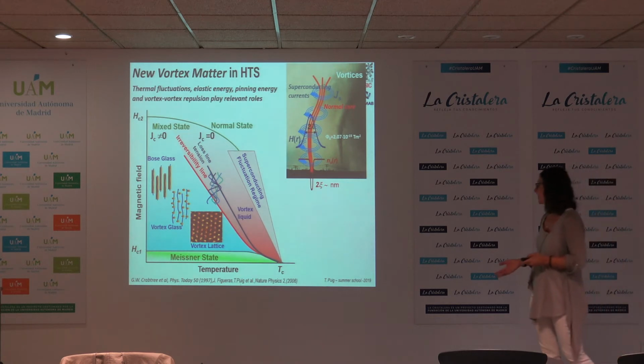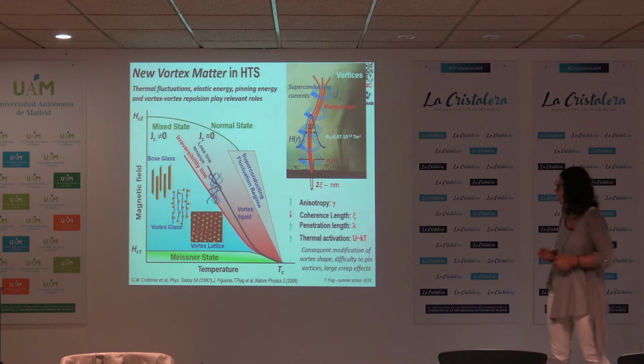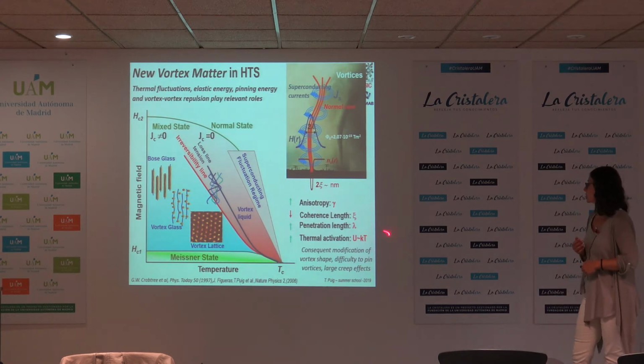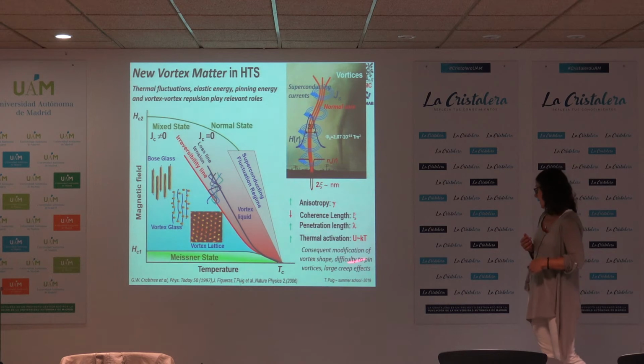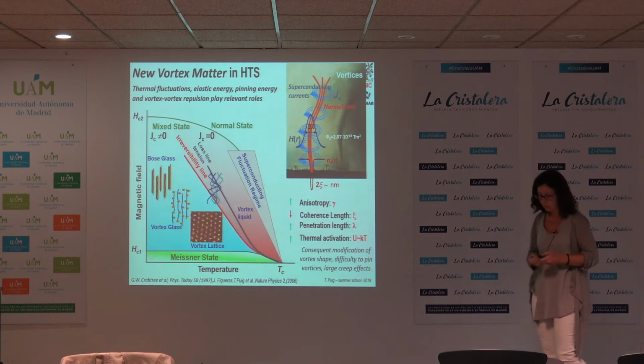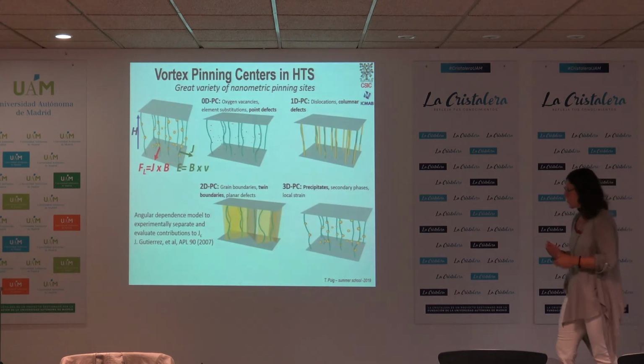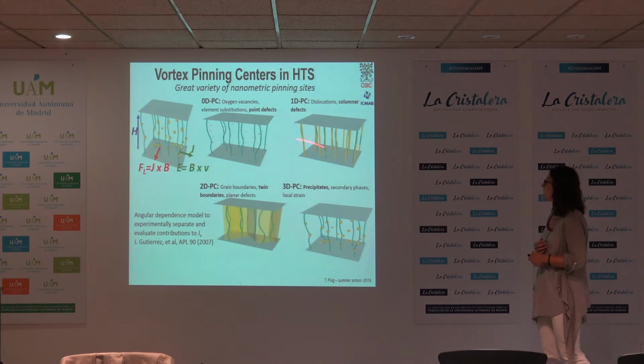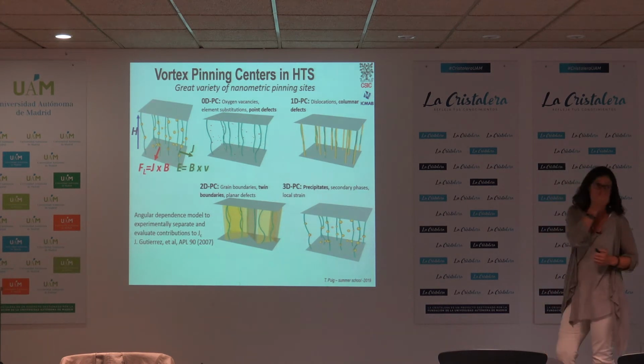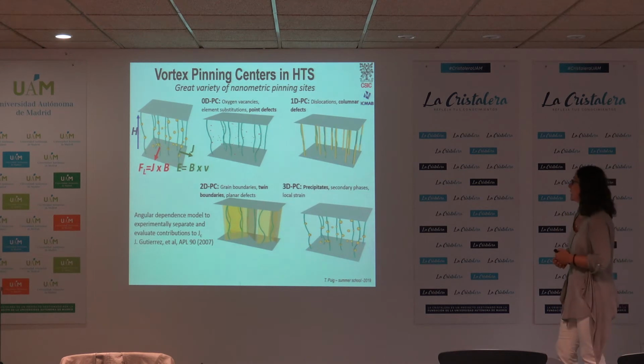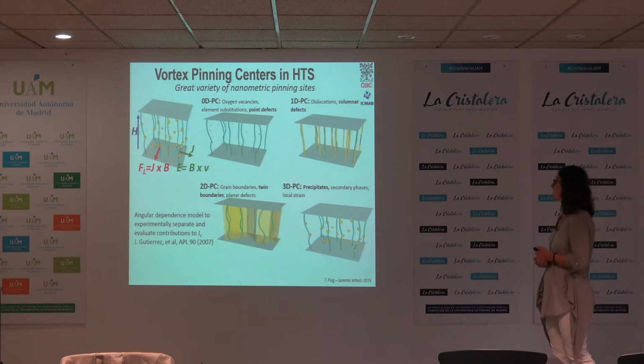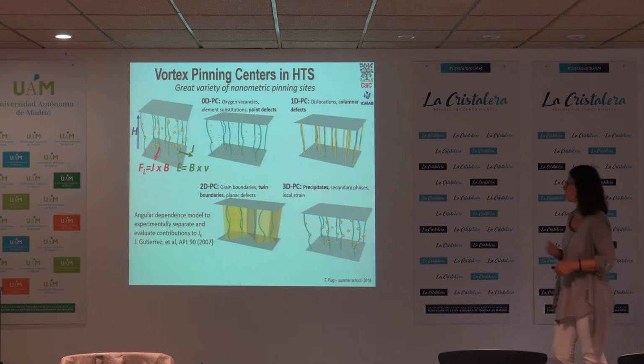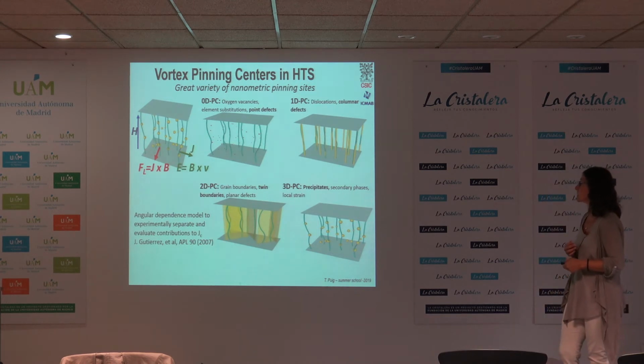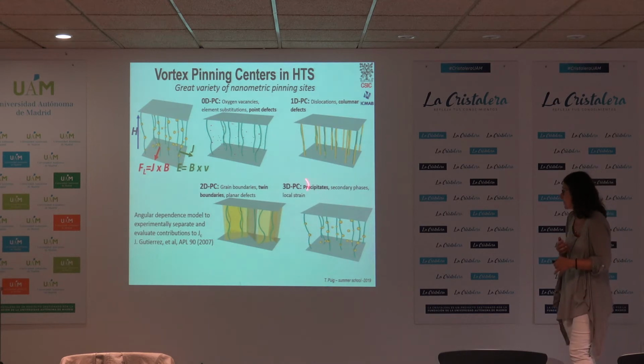And to control nanometric defects is not so easy, but also because we have high anisotropy, and also high thermal activation energies because we are working at high temperatures, it is more difficult for vortices to be pinned properly. And of course, we have many different types of defects that can pin vortices with different dimensions. We can have oxygen vacancies as point defects, or dislocations as 1D defects, or we can pin vortices in planes like twin boundaries, or in 3D defects like secondary phases.